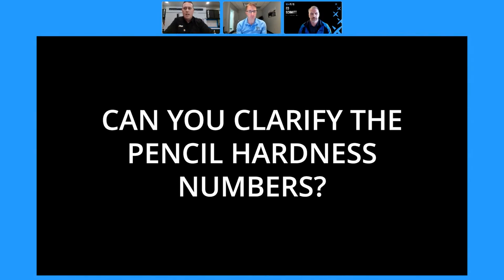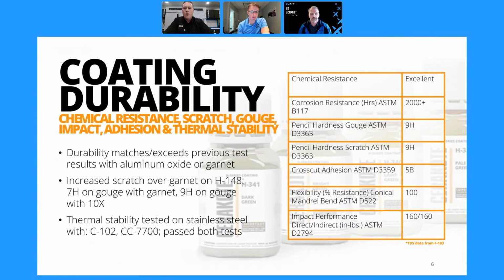So real quick, I'm going to go back here. Through the colors that I sprayed, the one color that I did see increased scratch and gouge resistance on was burnt bronze. All of our technical data sheet testing, the data that you see on there, is based off of our panels being blasted at normal pressure with 100 grit aluminum oxide, then sprayed at recommended mil thickness and cured at recommended cure temp. The only thing that I changed throughout that process was then blasting with EpiX MP. And I did see an increase in scratch and gouge resistance. That was about the only color where I saw the increase. I saw zero colors have a decrease in performance when blasted with EpiX.